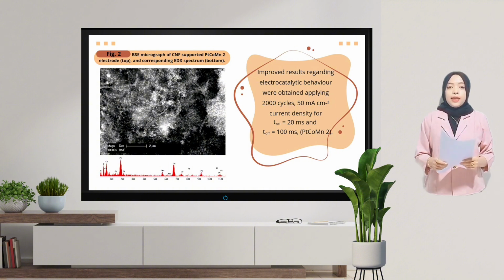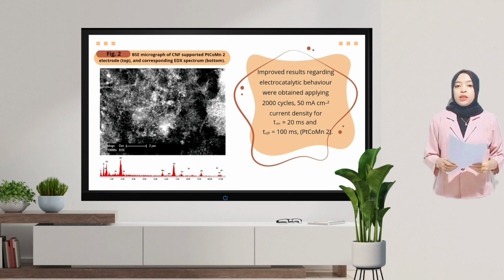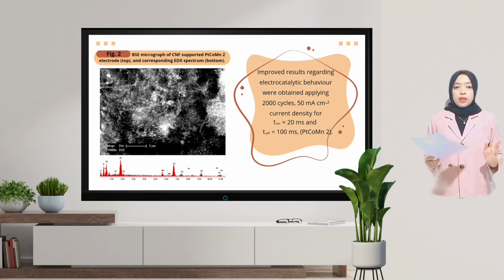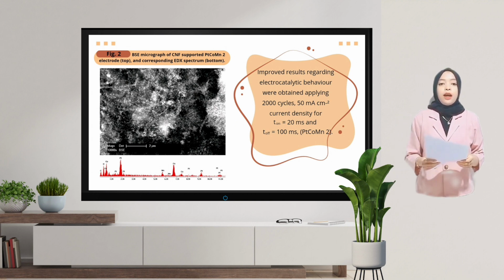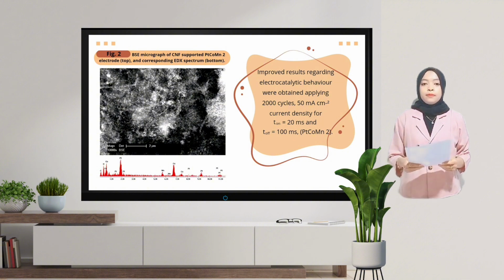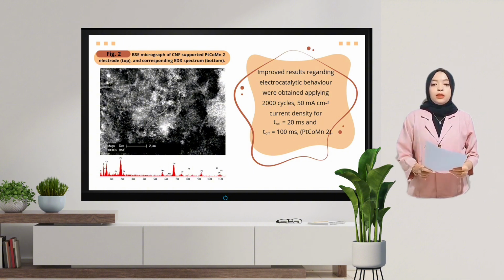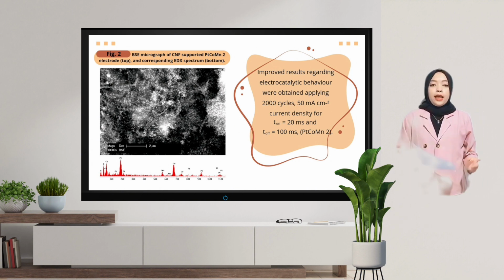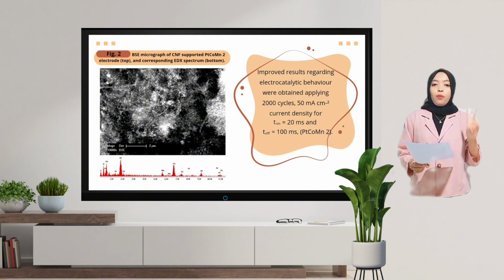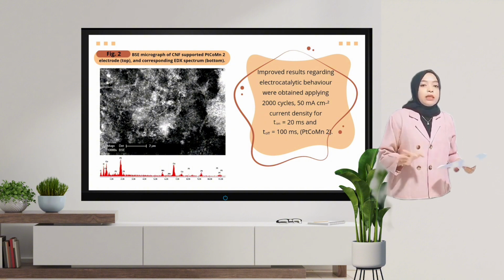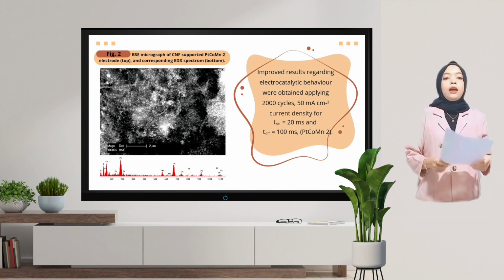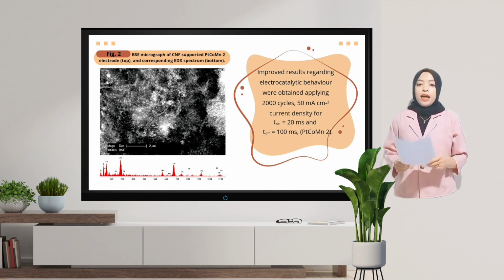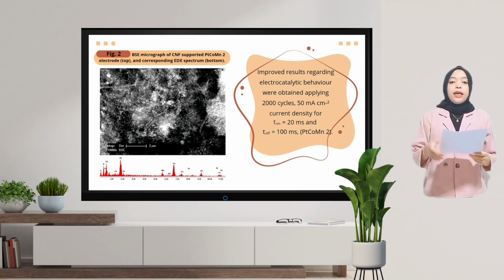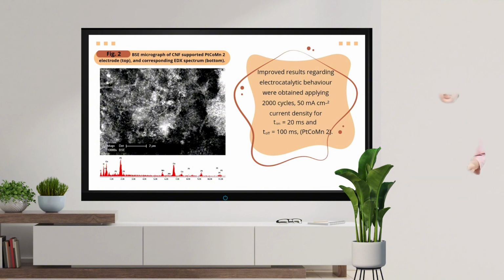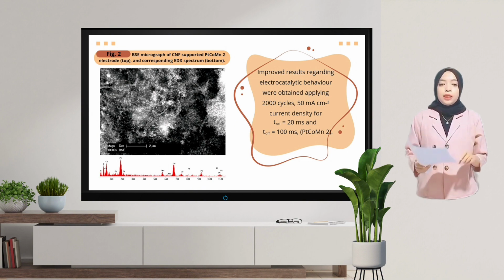A representative SEM micrograph of the obtained catalyst can be observed in Figure 2. The catalyst particles are evenly distributed onto the surface of the carbon nanofiber, having a spherical shape and uniform dimensions. The corresponding EDX spectrum, also present in Figure 2, bottom, highlights the chemical composition of the catalyst, revealing the presence of three main elements: platinum, cobalt, and manganese. Improved results regarding electrocatalytic behavior were obtained applying 2000 cycles, 50 mA per square centimeter current density, for T on equals 20 milliseconds and T off equals 100 milliseconds, PtCoMn 2.